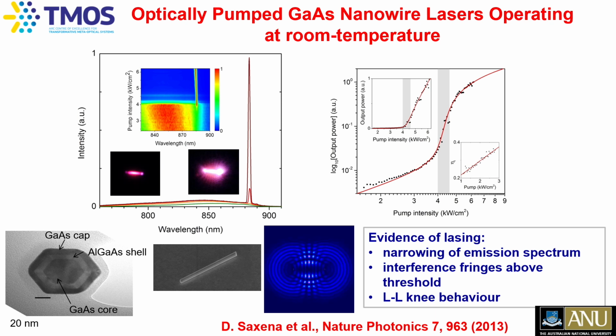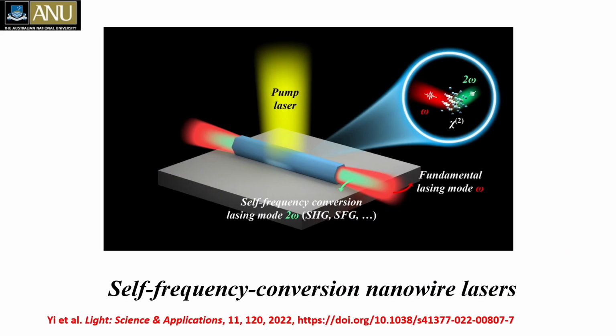In fact, Drew Saxena has done simulations to compare these interference fringes with the laser which he has really made, and they compare very well. And again, light output versus pump intensity shows threshold-like behavior, and the log-log plot shows S-type behavior, confirming that they're truly lasing. And these are the gallium arsenide lasers which have been very, very challenging within the community. By addressing surface passivation and getting rid of twin defects, we were able to show this about a decade back or so. So now let me come to the most recent work.